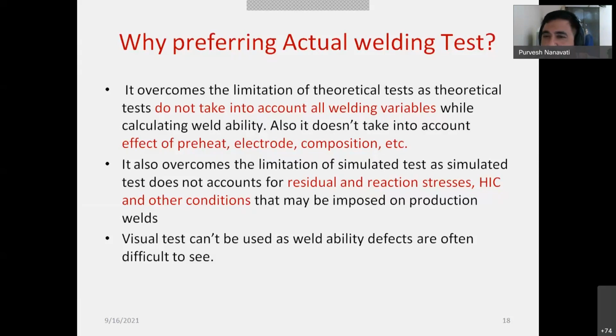In fact, otherwise, you have to go for the actual weldability test. You have to go for the procedure qualification test, right? You have to prepare the test coupon. You have to go for the procedure qualification test. If it satisfies, then your welding procedure specifications are approved. And this will not take into account the welding variables, the effect of preheat, electrode, composition, and many more things. And on top of that, residual and reaction stresses, hydrogen induced cracking, and other conditions. During heating and cooling, what will happen? You may consider welding as localized heating and cooling.